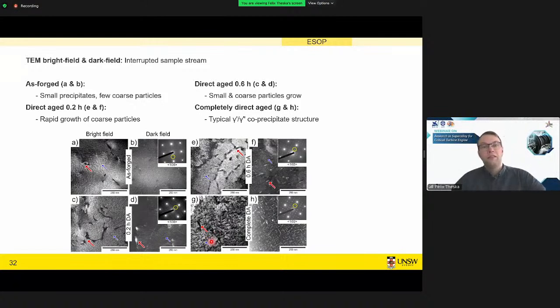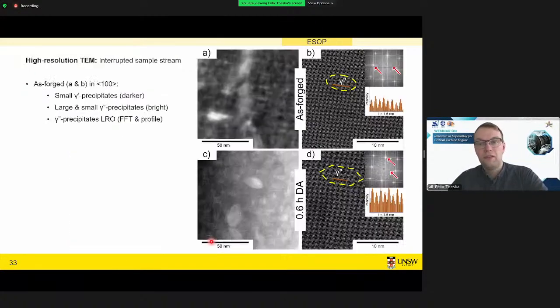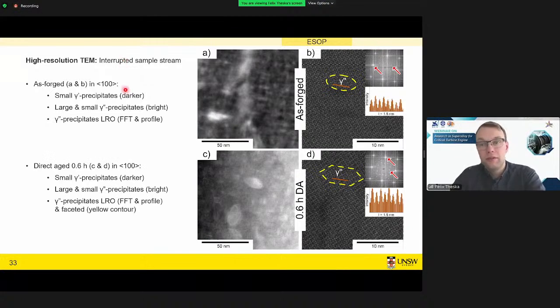We can also take these samples into the high-resolution TEM. We did this only for the as-forged condition as well as for the 0.6 hours direct aged condition. And what's pretty great with the high-resolution TEM is we can show that these are indeed precipitates. What's relatively easy to show is gamma double prime. Gamma prime you can see as this slightly darker region. I hope this comes through Zoom all right.